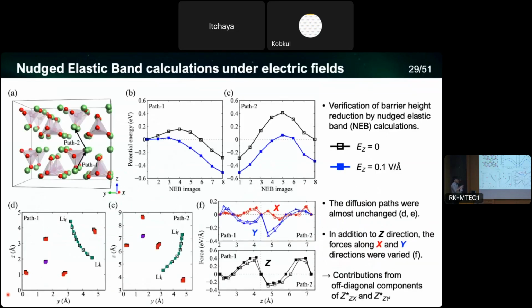Then, since we have higher mean square displacement, we want to confirm the lowering of the activation barrier. So we investigated through nudged elastic band calculations. These are the two paths and the obtained potential energy profiles. The black open squares are the potential profile without the electric field, and it decreased to the blue ones. So as you can see, we have a certain barrier height, but it decreased under the electric field. And in the reverse direction, it increased more compared to the case without electric field. So this is also a reasonable result.